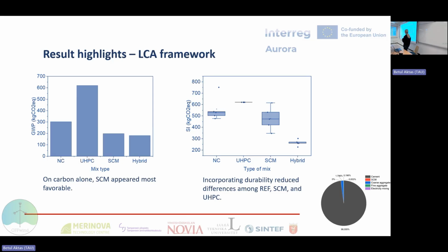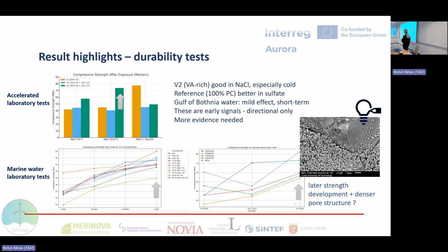So if we look at the comparison, this is just one of the results. If we compare the typical analysis with cradle to gate from the extraction of materials, we can see that UHPC, because of the high amount of cement, is the highest when it comes to CO2 emissions. Then the SCM and the hybrid mix are the lowest. On the other hand, if we take into account the durability parameters with different scenarios that are input there with the cases that we studied that I showed you before, we can see that those differences are not so high between those different mixes, but the hybrid mix performed the best when it comes to the carbon footprint.